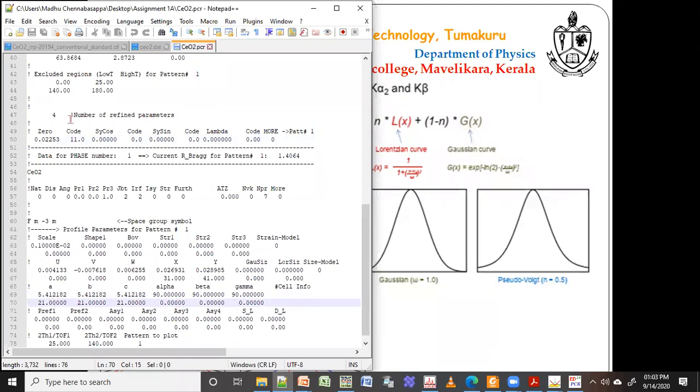Once we did a, b, c and zero, our chi-square was still around 15 or 18, right? So then we did fitting of X and Y. X and Y again come from your instrument. If your instrument is giving Lorentzian or Gaussian contributions, these are again instrument parameters. So till now we have not touched the atoms or the atom positions. We have tried only the a, b, c parameters and instrument parameters. This is your profile fitting. Before going to Rietveld, you have to do a very good profile fitting.